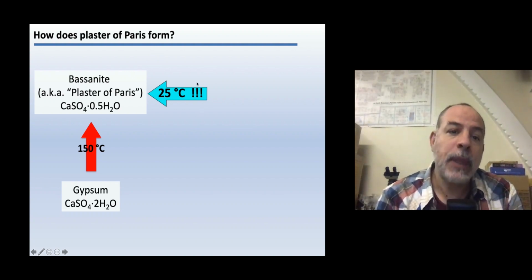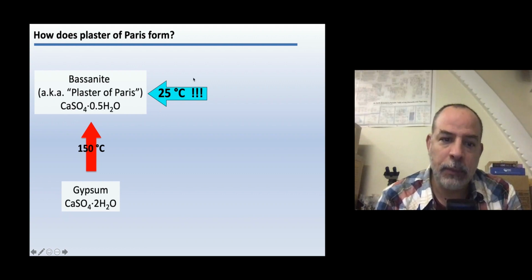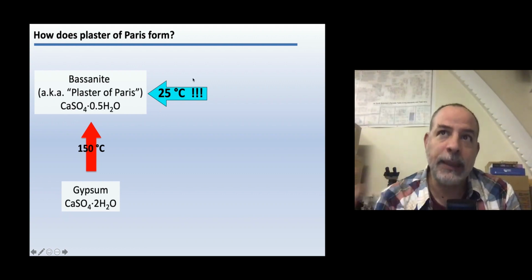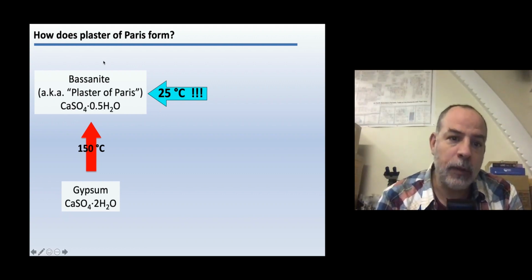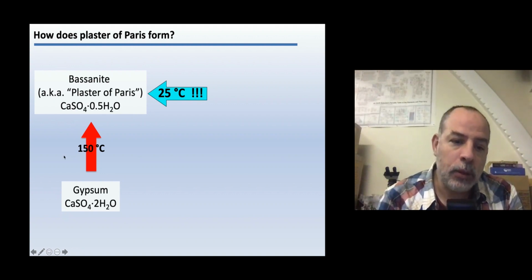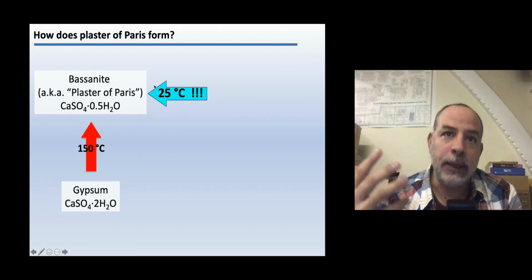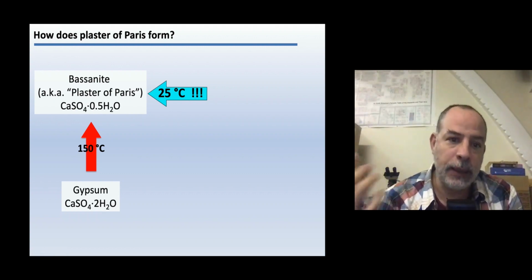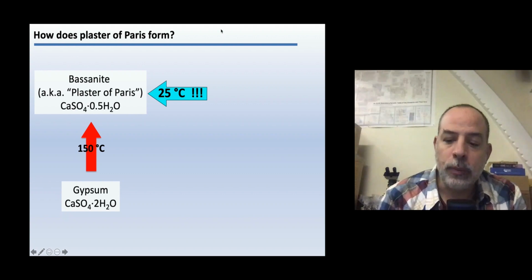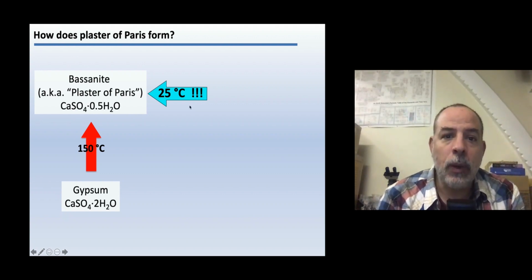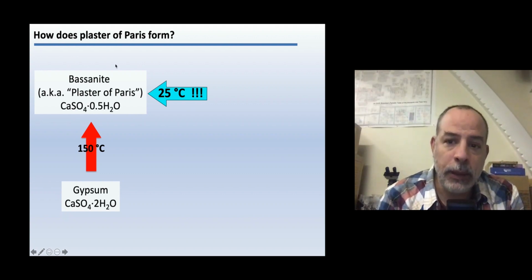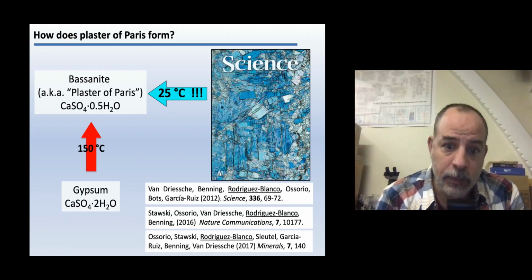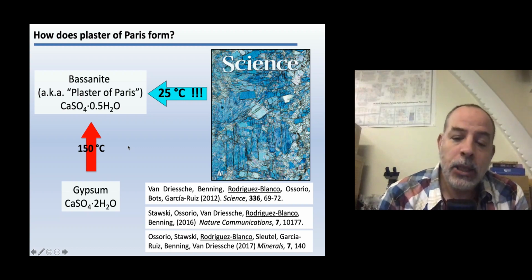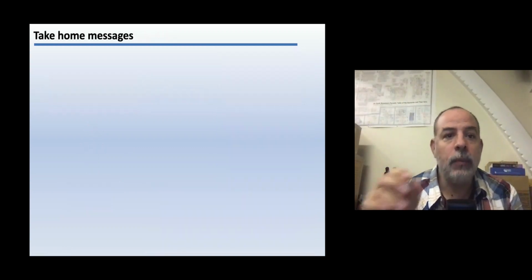Okay, because if we could stabilize bassanite from ambient temperature, that means that that will be a fantastic way of producing plaster of Paris without having to dehydrate gypsum. The problem here is that this bassanite is very unstable. It's not easy to stabilize it for a long time. Okay, so this research was beautiful. It was a fantastic collaboration, and it was translated into very nice papers, including a front cover in the journal Science.